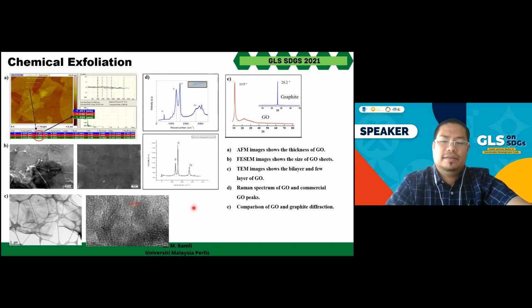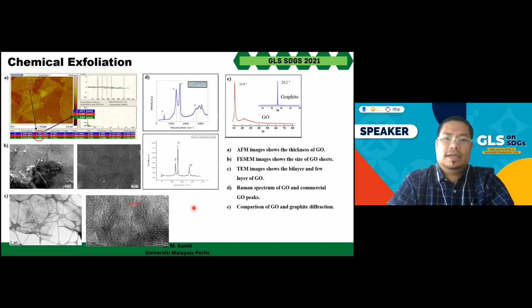So once we get the synthetic graphite, we further exfoliate. There are a lot of methods or techniques that you can use in order to produce graphene. The method that we chose is a chemical exfoliation using our own recipe. Again, we basically use a strong oxidant in order to have the oxidation process happen. And then we attach functional groups on the basal plane of the graphene in order to get the graphene oxide.